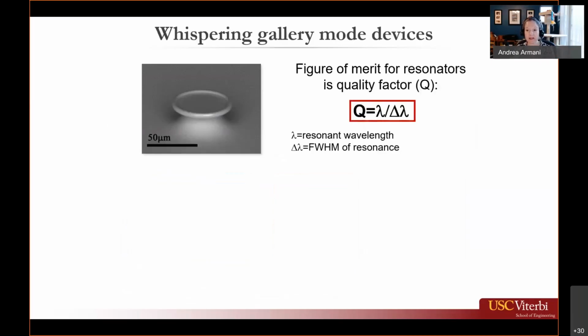One of the key metrics of a whispering gallery mode cavity is something called the quality factor, or the Q. The quality factor describes how long the device can store light. One way of characterizing it is by that specific resonant wavelength divided by the full width half max of that resonance. This is directly proportional to the photon lifetime inside the cavity. However, the easiest way to experimentally characterize it is by measuring that resonant wavelength using a tunable laser and scanning across all the resonances of the cavity, and then you get a spectrum